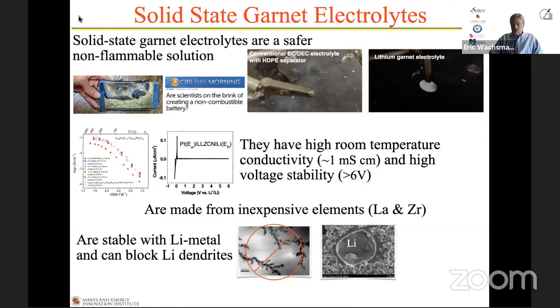In contrast, there's a SEM image there of lithium metal inside some of the pores we have in our ceramic electrolyte. It's quite stable and allows us to cycle lithium metal and then therefore use lithium metal as an anode, which is much higher, as I said, capacity and therefore energy density out of our batteries.